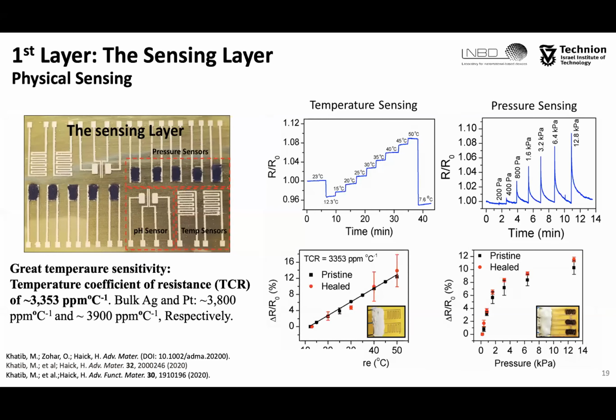For the pressure sensing, we used a resistive composite made of self-healing polymer and carbon black. The application of pressure led to an increased distance between the conductive fillers and therefore an increase in the resistance. We've run examinations in the lab, but due to time limitations in my presentation, I cannot show all the results.